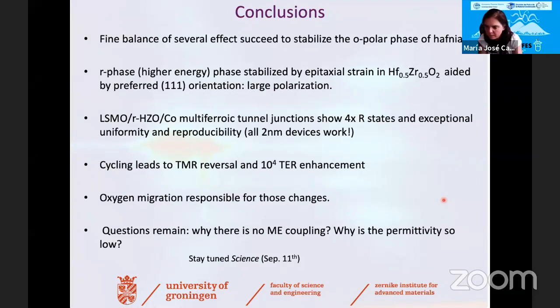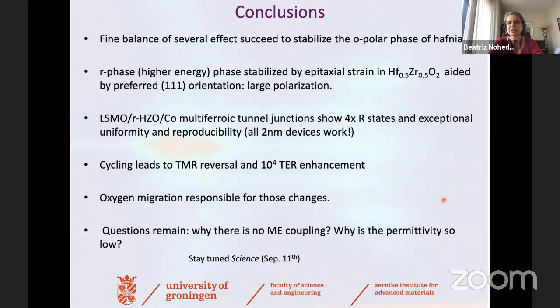Juan Beltran asks, how does the oxygen partial pressure influence the polarization exhibited in this system? It does, but it's not key. If I compare with other materials like the nickelates that we are also growing in the lab, or any other perovskite material, or spinels, for example, the oxygen pressure during growth and also during cooling down is very critical. Hafnia, once we have found the growth conditions, the oxygen pressure is not key.